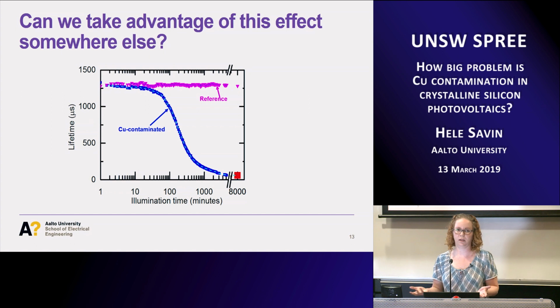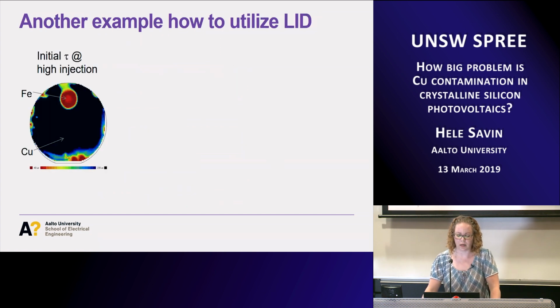Unlike for iron, where there is a very well-known method to measure iron-boron contamination, through iron-boron breaking and dissociation and calculating the concentration from that. So we were thinking maybe this kind of phenomenon could also be used for the characterization of copper concentration. What we have done is to measure minority carrier lifetime, importantly in the high injection range. We have a clean starting wafer, and we intentionally put a few copper atoms here in the form of a droplet. As you see, when you measure lifetime, the lifetime has dropped because of the interstitial copper. And now we see the danger of copper.